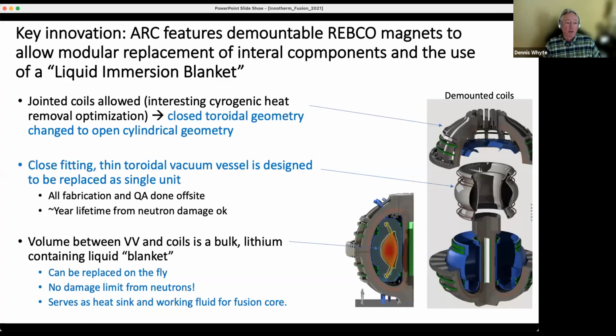on this. So the key innovation in ARC is that it actually features demountable REBCO magnets, which will allow modular replacement of internal components and the use of a liquid immersion blanket. So what do I mean by that? So I've got this toroid. So now the idea in ARC is that you can actually lift off the top part of the magnet, and the closed toroidal geometry, which is necessary for the fusion confinement, opens up to cylindrical geometry so that you can access those things which are inside, which are obviously the things taking out the heat.